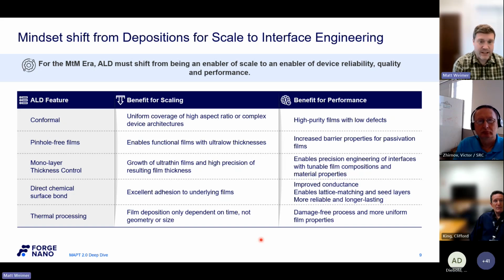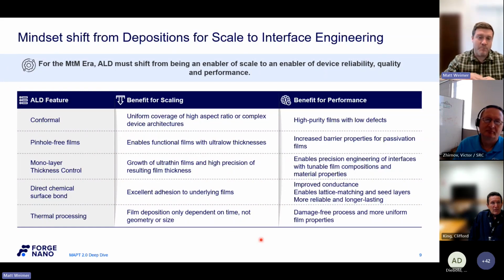Yeah, those are great points, Alan. Those are some of the dirty secrets of ALD, but I will say it also depends. There are processes that start with that ideal growth right away. It really depends on the surface. Think about this from a surface chemistry standpoint, what a bulk film looks like. Let's use aluminum oxide, for example. Once you're growing on aluminum oxide, that will look the same with each half cycle. You're doing the same half cycle reaction, or you're doing proton transfer.